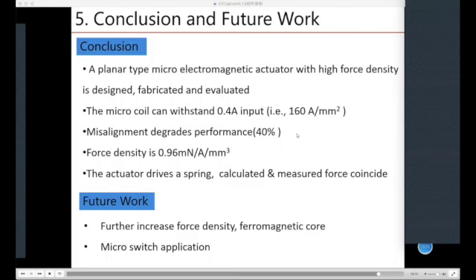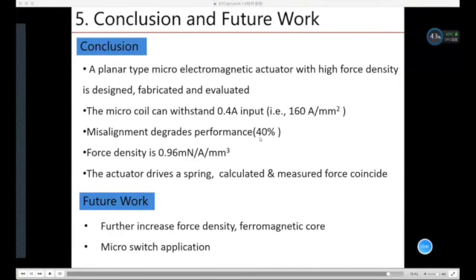Then comes the conclusion and the future work. In this research, a planar-type microelectromagnetic actuator with high force density is designed, fabricated, and evaluated. The microcoil can withstand 0.4 ampere input, that is 160 ampere per square millimeter, and the misalignment degrades the performance to around 40%. Even if misalignment exists, the force density of the actuator reaches 0.96 millinewton per ampere per cubic millimeter.